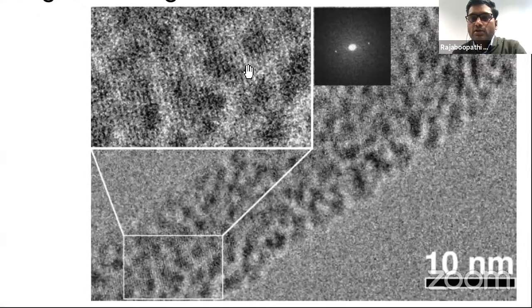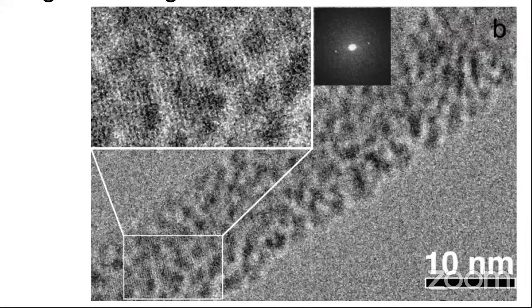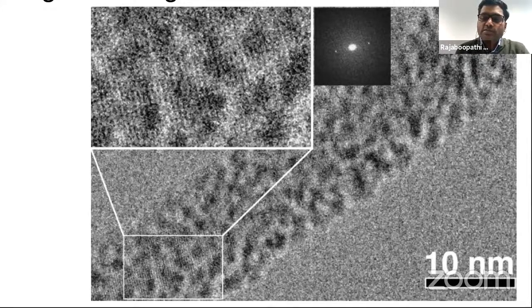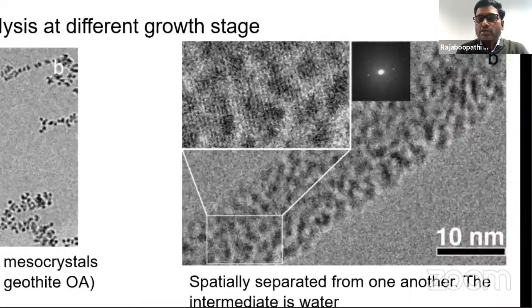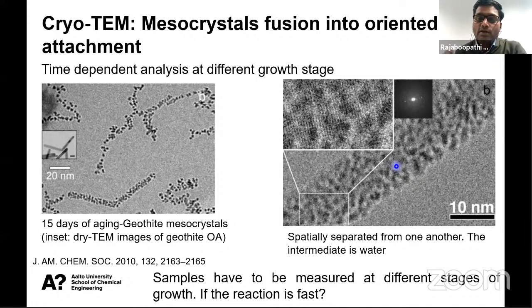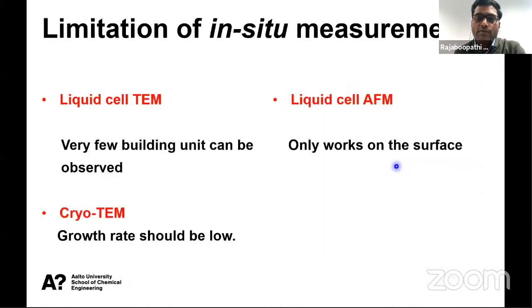The bright spot is a crystalline unit, and the dark spot is a non-crystalline unit. Here it is the water. Water is the non-crystalline unit in the mesocrystals. If you keep these mesocrystals for a particular time, based on the stability, they may fuse into oriented attachment. And if you keep the solution for some more days, it may fuse into single crystals. Everything is based on the stability. If you need mesocrystals, you need highly stable mesocrystals or nanoparticle units.